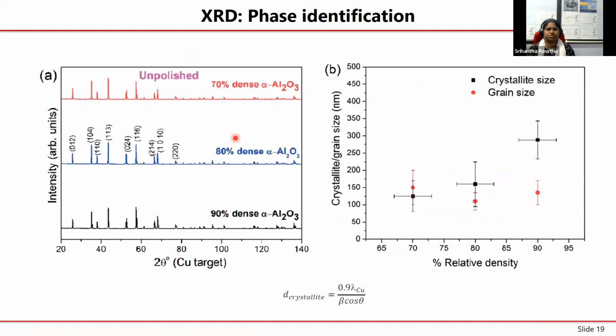All right. So for these specimens, because we started off with alpha Al2O3, if we are sintering at higher temperatures, would it convert to gamma Al2O3, or would it convert to some other phase? That needs to be confirmed. For that, we have done some XRD analysis and found that the phases are not changing. But then we use this to find the crystallite sizes and compared them with the grain sizes, using this Scherrer analysis.